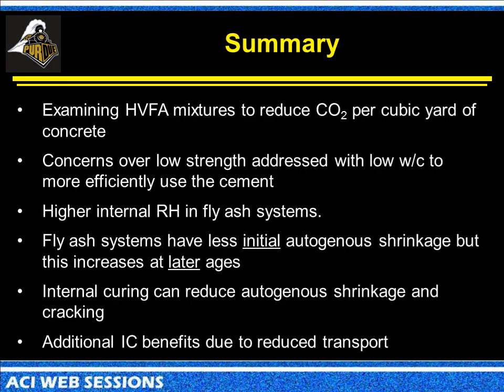So the basic idea here is we're looking at high-volume fly ashes as a way to reduce the carbon dioxide per cubic yard of concrete. The concerns for low strength, we believe, are very easily dealt with water to cement ratio and allow you to use different fillers inside of the system. We're using internal curing to more effectively use those cements when we're at lower water to cement ratios. Allows us to keep the relative humidity higher.